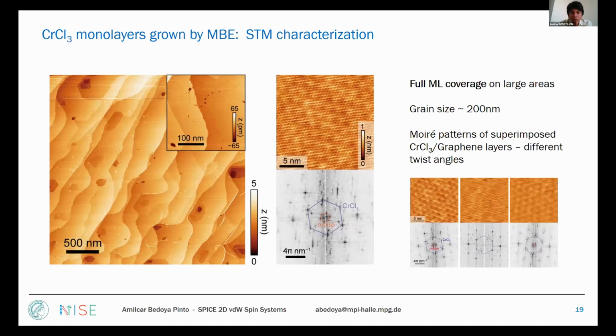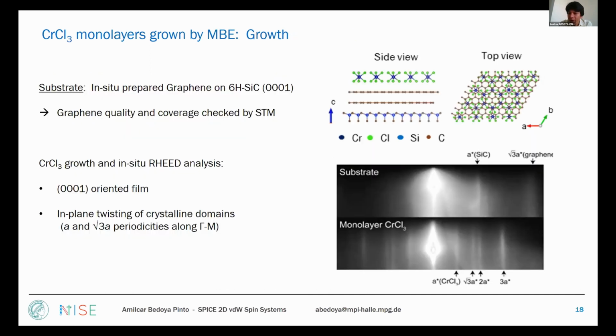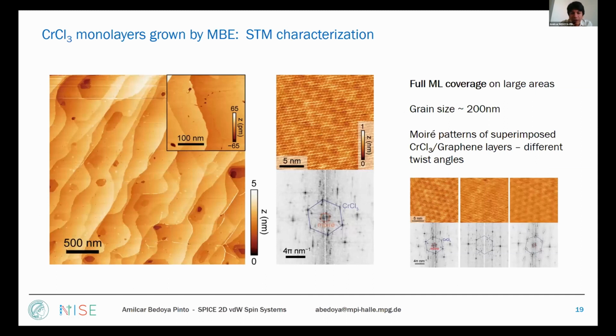So then, of course, we want to assess with STM that we have indeed full monolayer coverage. Actually with the RHEED, when you see the disappearance of substrate lines, you will also think that it's a full monolayer coverage. Nevertheless, we went to the STM, and as you can see here in this topography image, this monolayer is like a carpet, and it deposits on all the terraces, following the morphology that is given by the silicon carbide substrate.